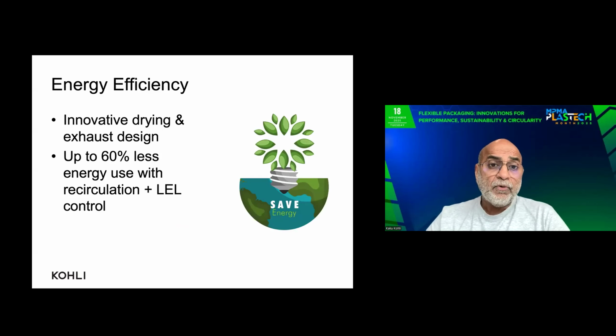The most important point to look at in such equipment is how efficient it is when consuming energy. You shift to water from solvent, you're looking at high temperatures, more heat loads, and a longer drying tunnel length. So the equipment has to be innovative and with a very good drying and exhaust design. And it should have a precise and well-designed air recirculation system, sometimes with LEL control if solvent is involved, where you can reduce your solvent consumption by over 60 to 70%.